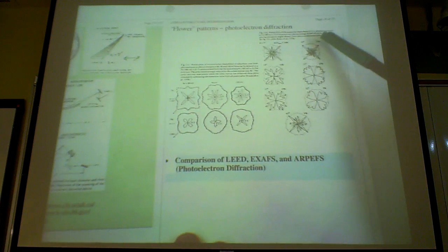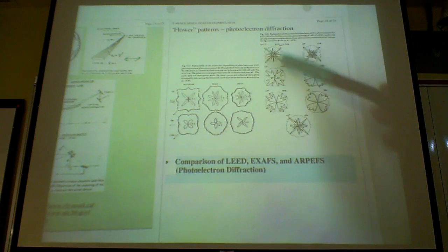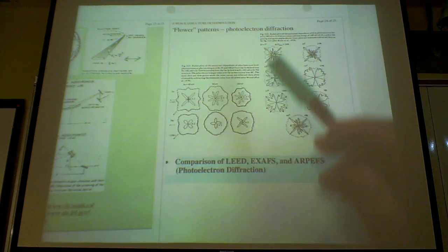Okay, and if you can't use a synchrotron, and I'll talk briefly about this shortly, you can also do it with one fixed wavelength. You can just fix a wavelength like a laboratory-based source, and just measure the angular distribution. Right? You can just measure the angular distribution. You get something called a flower pattern.